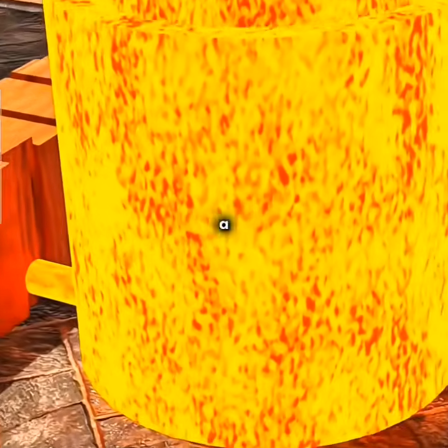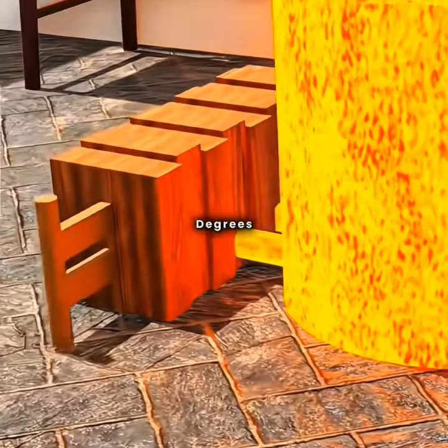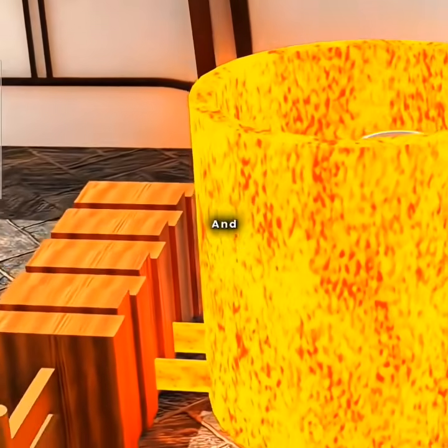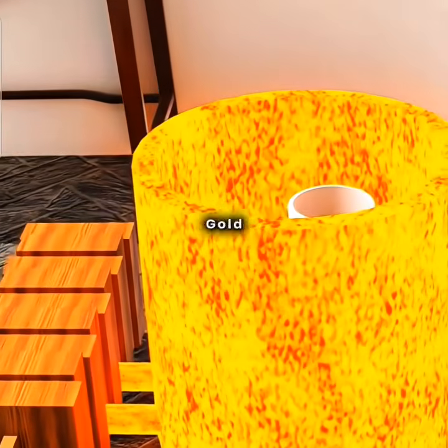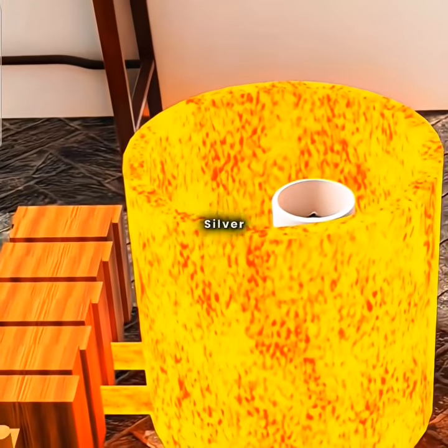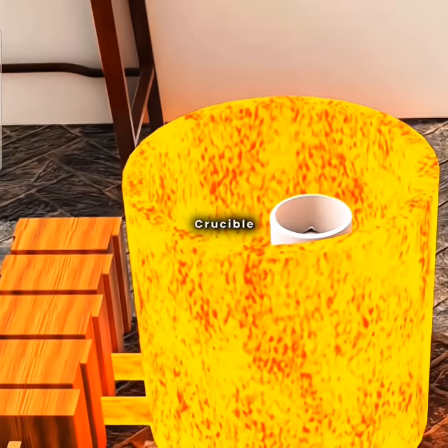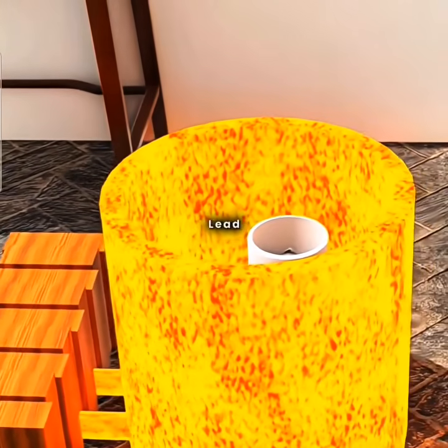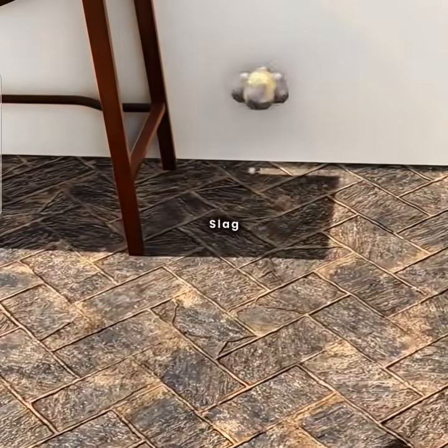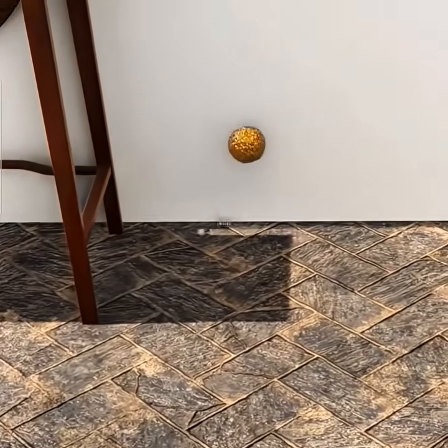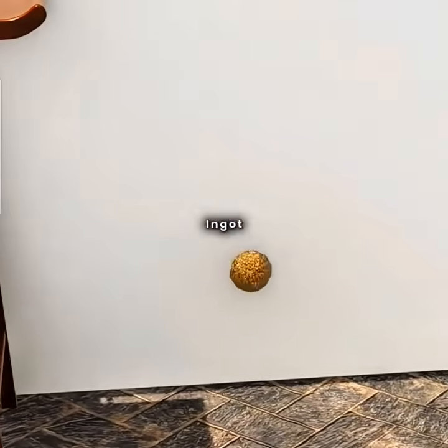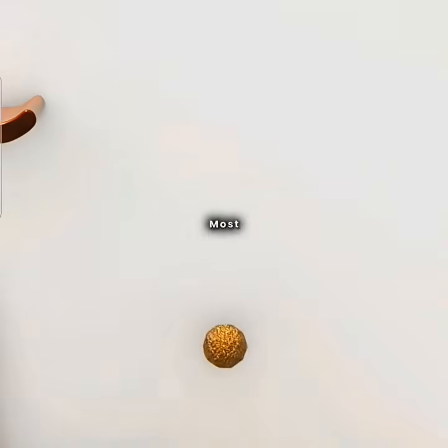to heat it. Lead has a melting point of 327 degrees Celsius, so it melts first, and like a magnet, dissolves the dispersed gold and silver, forming a gold-silver-lead alloy that sinks to the bottom of the crucible. Other impurities that don't react with lead float to the surface, forming slag. After skimming off the slag, you obtain a block of impure alloy ingot. This is called smelting. Finally, the most important step.